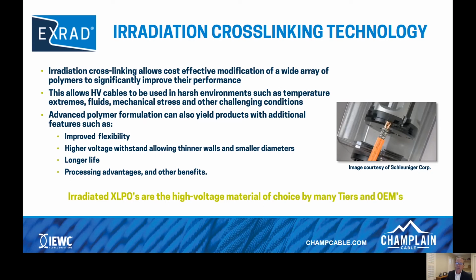Then on top of that, you add advanced polymer formulation, like we had on the material science slides, and that can yield products with additional features such as improved flexibility, higher voltage withstand, which allows thinner walls and therefore smaller diameters. You can formulate products with a longer thermal life and a resistance to spikes in temperature as well. So, you know, power cable designs in EV systems are typically specified to a worst case design scenario. So just take a city bus, for example. Its average scenario is going to be driving its city route day in and day out.